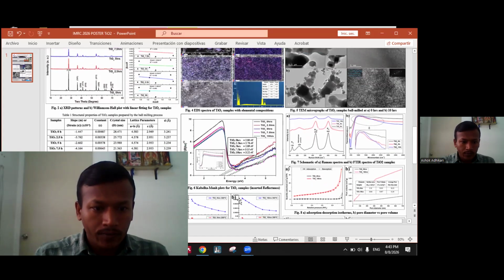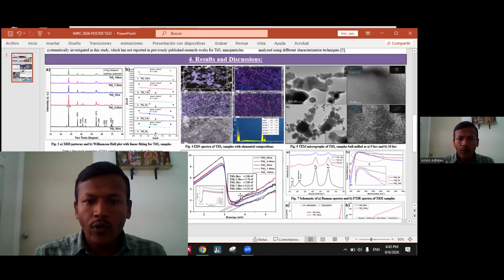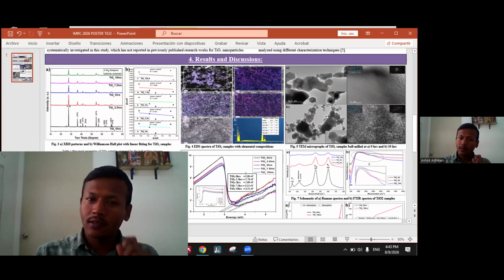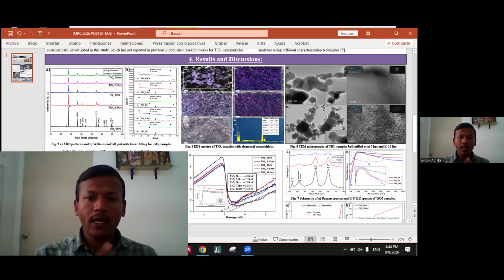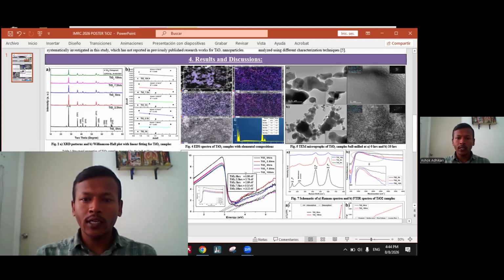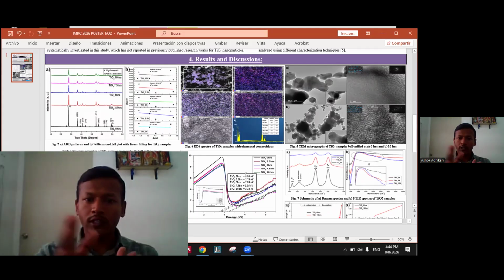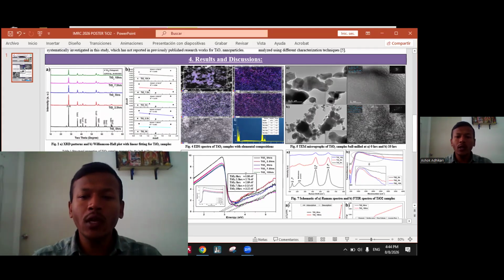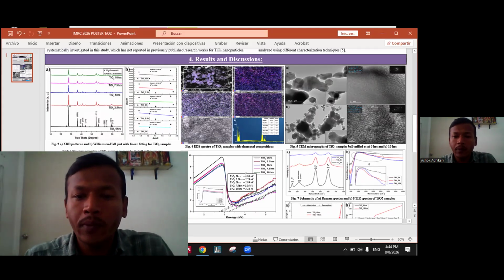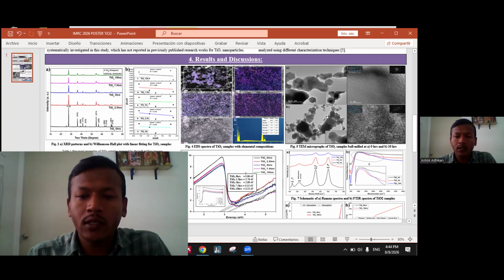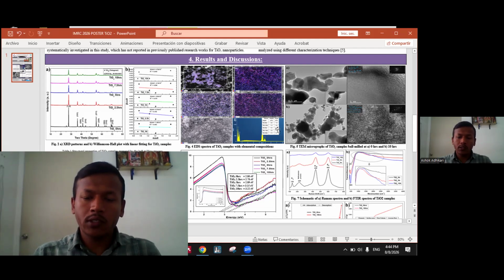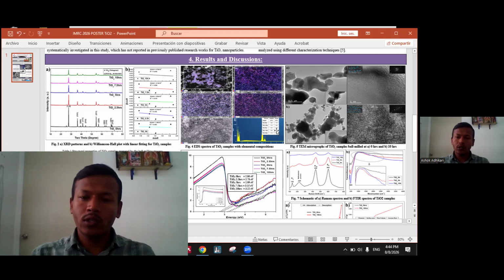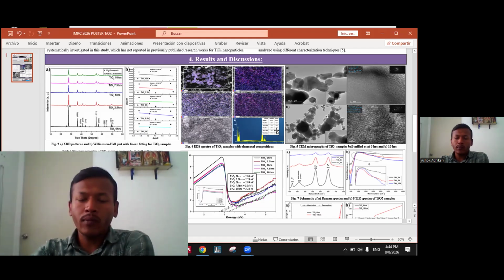From figure 4, we can see the EDS mapping and EDS spectra. From the mapping, we have seen the distribution of oxygen and titanium. So for all samples, we have seen the homogeneous distribution. And from the spectra, the peaks of oxygen and titanium show the presence of oxygen and titanium in the samples. And also, we have presented the atomic concentration of the oxygen and titanium for our samples.